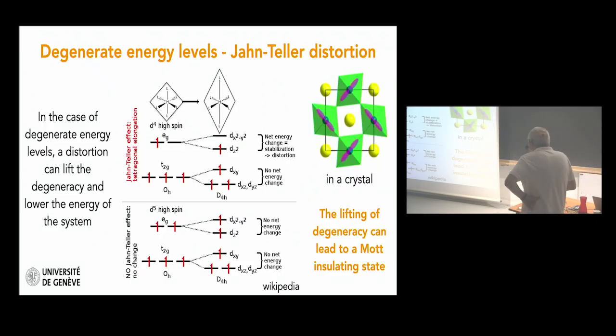Now, one more thing, if you have degenerate energy levels, often the system goes to a structural transition to lift this degeneracy. And this depends now on the filling of the d band. So this is a nice example here where you see a system with four electrons, so d4, high spin. So with our picture, we have our t2g orbitals here, the eg here, high spin. So you put your three electrons in the t2g, and you have one electron in the eg, degenerate state. The system doesn't like this, and the system goes through a Jahn-Teller distortion. So you distort the octahedra. This is what you see here, and this is what you see here in a crystal.